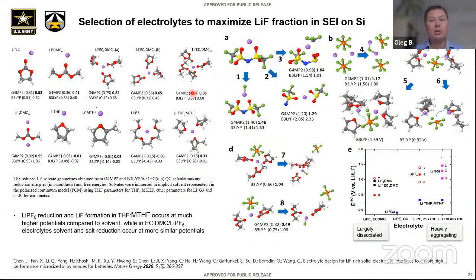What about anions? If we have LiPF6-like anions and they heavily aggregate, which does happen in pure DMC but doesn't happen in pure EC or in EC-DMC 1-to-1 electrolyte. But if some of these fragments would occur, then the reduction potential would be about 1.17 volts, and that's another point that DFT here, this functional at least, significantly overestimates this reduction potential because of inadequacy with the lithium, fluorine, phosphorus bond description.